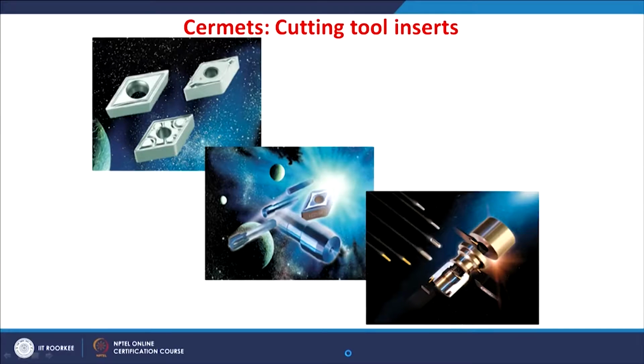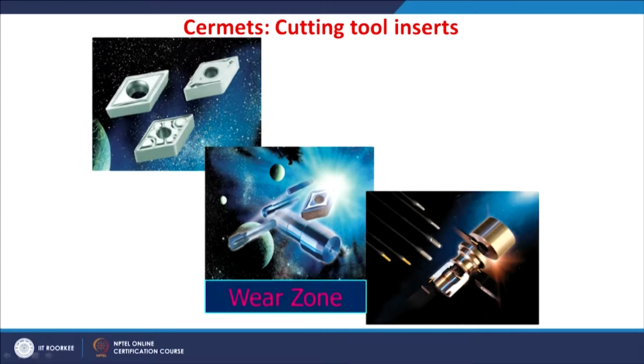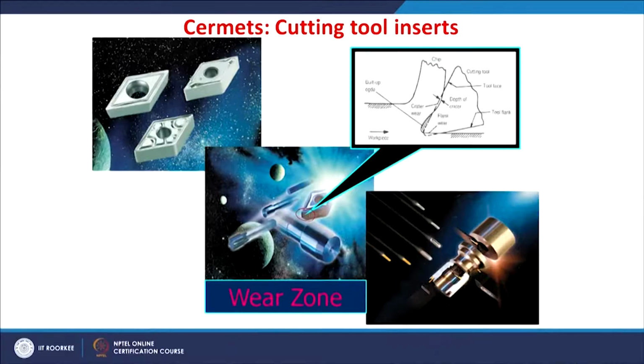Regarding the engineering applications, these cermets are mainly used in cutting tool applications as an insert for the cutting tool. So, in machining, if you look at the nose tip of this tool and the workpiece, a large amount of friction is generated. This friction induces the wear, but this friction induces high temperature as well. So, the friction induced heat and the damage both simultaneously occur and lead to material degradation. So, particularly in these cutting applications, the mechanisms shall be studied in the crater wear or the flank wear of these cutting tool inserts.